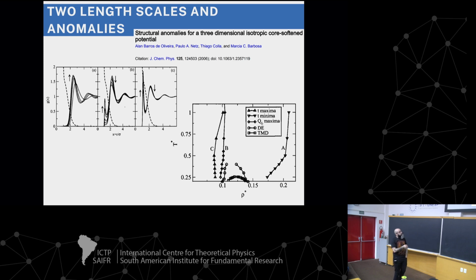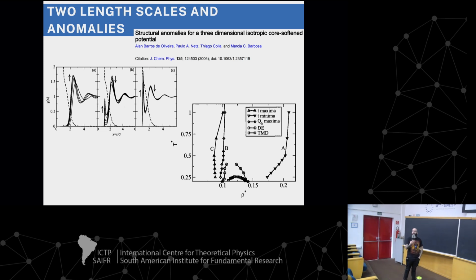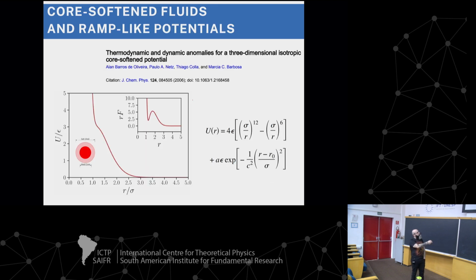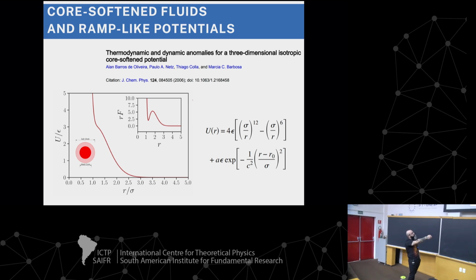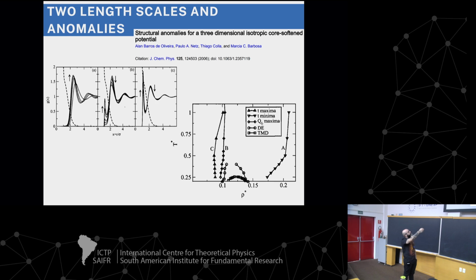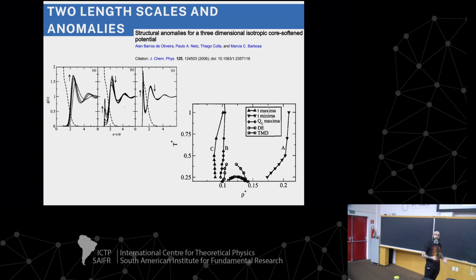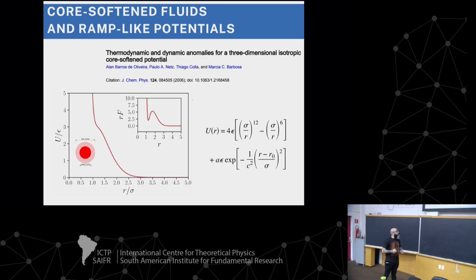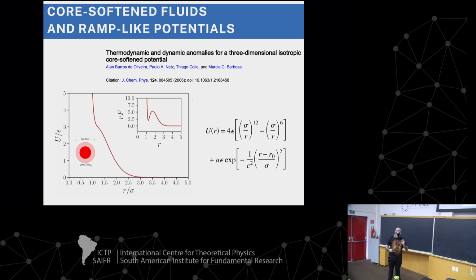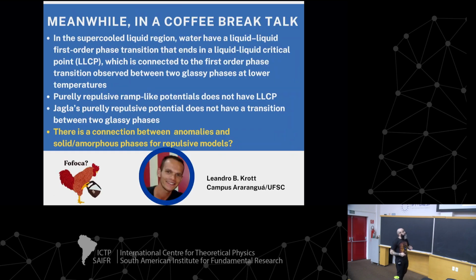What they saw is that these anomalies are related to the competition between two length scales. In this model, the molecules can get a little bit further or a little bit closer. If your pressure is low, for instance, you'll be mainly at this distance. If you increase the pressure or the temperature, you have enough energy to climb the ramp and get to this other state. We can see this competition in the g(r): the population of the second length scale goes down and the population of the first length scale goes up. This explains the anomalies, this competition between two scales. But one thing that's really important: this potential is pretty repulsive. This is a main ingredient for this part.